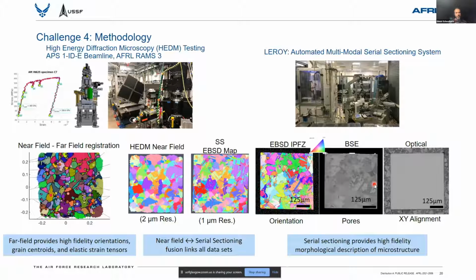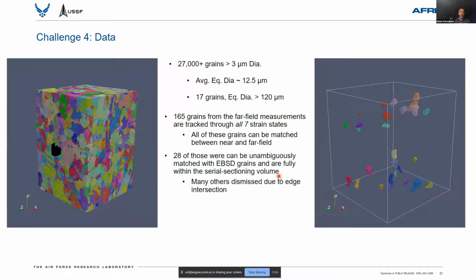So this experiment, the loading experiment I just described, was carried out at APS. In the beamline, the specimen was unloaded and brought back to AFRL, where we performed a serial sectioning operation to produce a higher resolution, essentially a higher fidelity description of the microstructure. And then a fusion operation was performed in order to bring together this high resolution description of the microstructure with a grain by grain and stress state by stress state description of the evolution of the elastic strains during this tensile test. This produced a data set that has about 27,000 grains described, considering the grains that are more than about 3 microns in diameter.